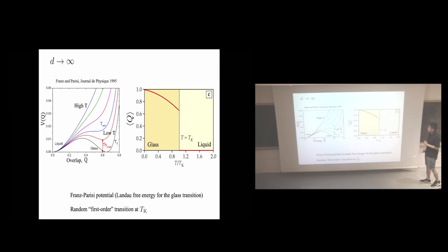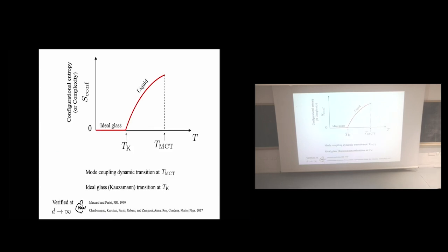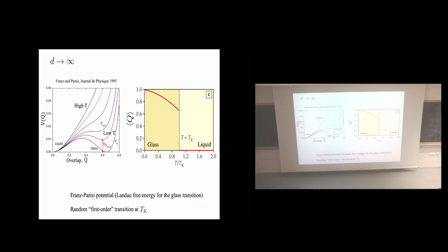On the right, I show the expected mean value of the overlap parameter as a function of temperature. At high temperature, as I mentioned, the overlap is zero in the liquid state. But below TK, you see a discontinuous jump of the overlap. So this is a sort of first order like transition. Okay. However, as you can see in this entropy plot, entropy doesn't show a jump, so no latent heat. So it means that it's not a standard first order transition. So that's why people call it a random first order transition.